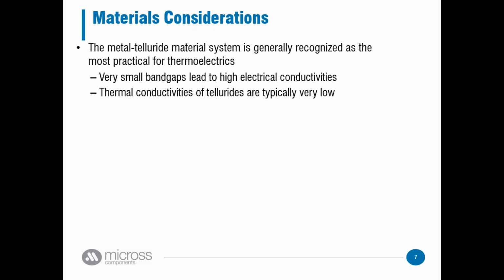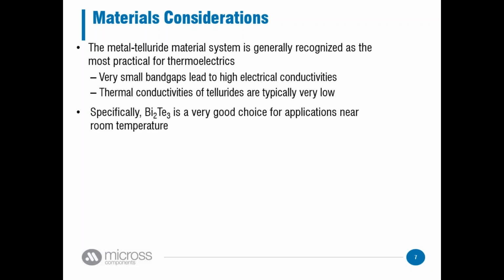They're more semi-metal than they are semiconductors, so that's going to give you your low thermal conductivity and the high electrical conductivity. And the thermal conductivities are typically very low because you have big atoms. They're down at the bottom of the periodic table. Those big atoms vibrate very slowly, and so essentially you have a relatively low thermal conductivity. The most common of these metal tellurides in general use is bismuth telluride.